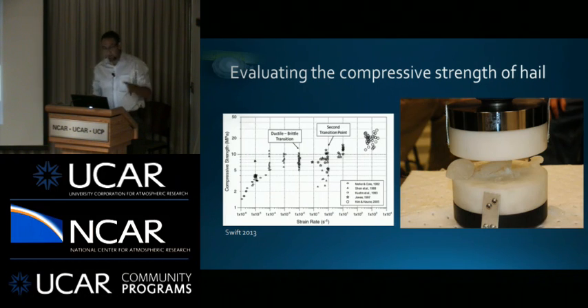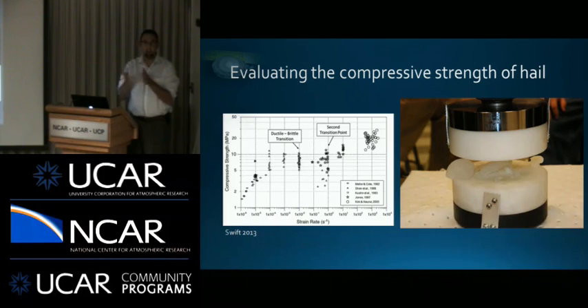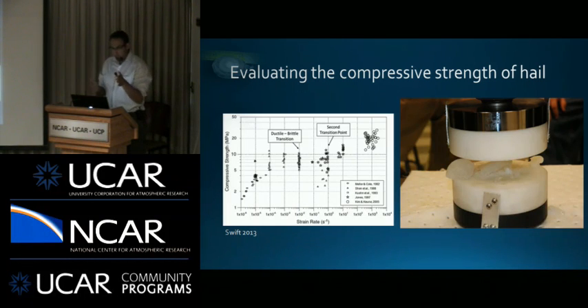I should preface, there is a dependence on temperature, but if you look at ice, say from minus 10 to minus 30 C, there will be a difference in the amount of load it can support. If you measure the surface temperature of the stones when they're tested, you're usually right around there, but just below. I'll get to the melting issue in a little bit. So you couldn't take one of these large apparatuses out to the field and perform these tests. They're just too cumbersome.